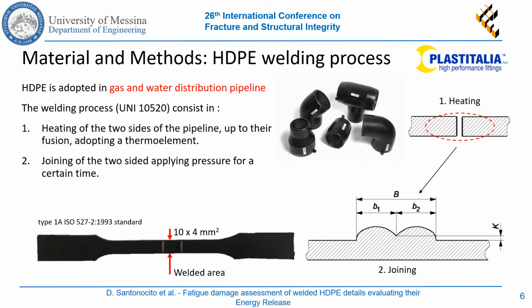High-density polyethylene is a material widely adopted in pipelines for gas and water distribution. Sometimes it is necessary to weld different sections of the pipeline, for example fittings. According to the Italian national standard, the welding process consists of two phases. At first, the two sides of the pipelines are heated up to fusion, adopting a thermoelement. Then, the two parts are joined applying a prescribed pressure for a certain time.